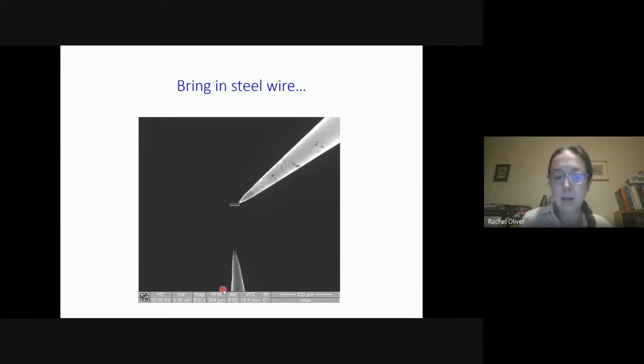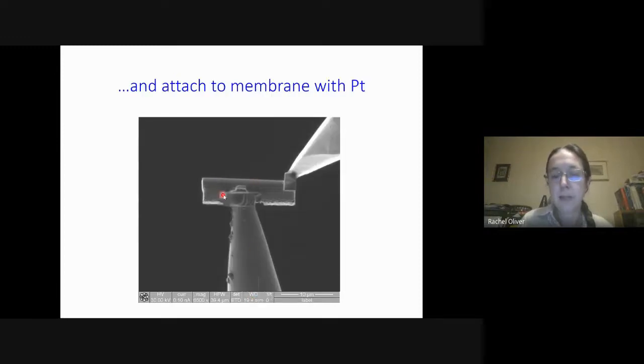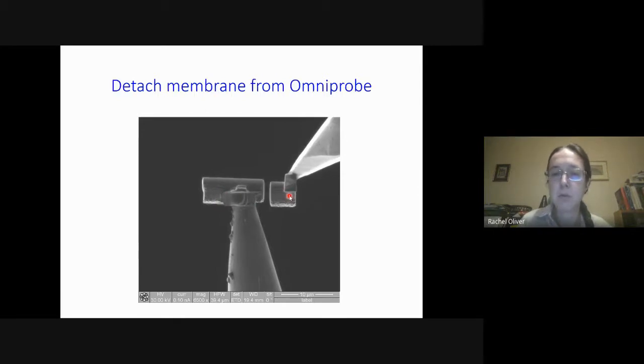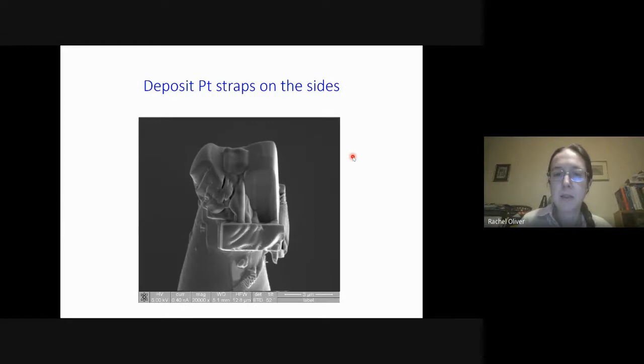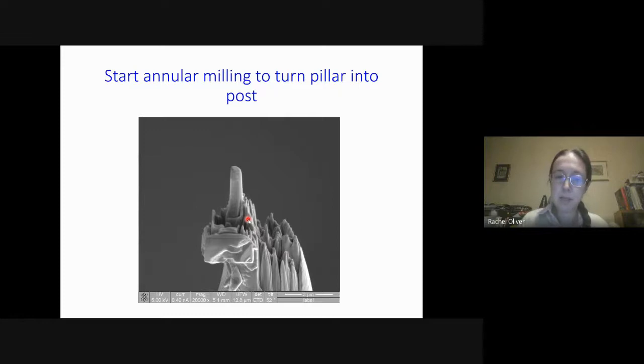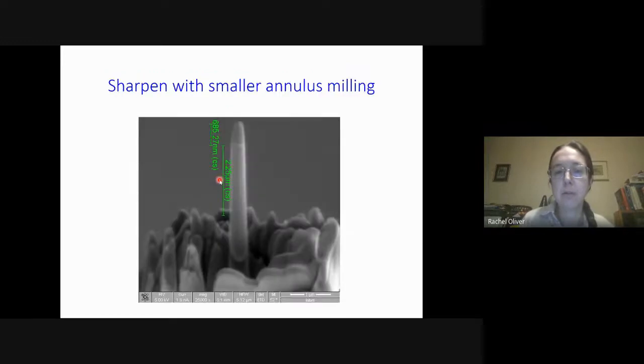In our early experiments, our sample holders were just steel wires, so we brought it to a steel wire, taped it onto the steel wire with another band of platinum. We can remove the Omniprobe, and then we tape down all the way around with lots and lots of nice conductive platinum to make that electrical contact we need in order to be able to do the atom probe experiment. And then we start to mill in annular, kind of donut shapes that bring the radius of the pillar we initially had down to a post and then to an ever thinner needle.